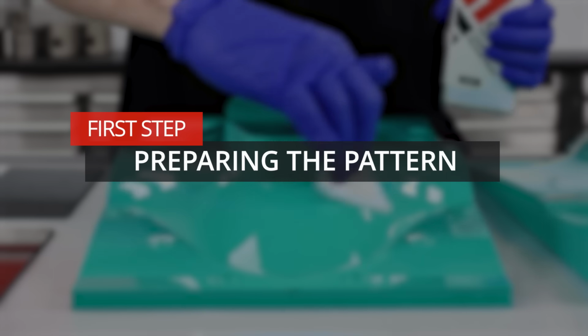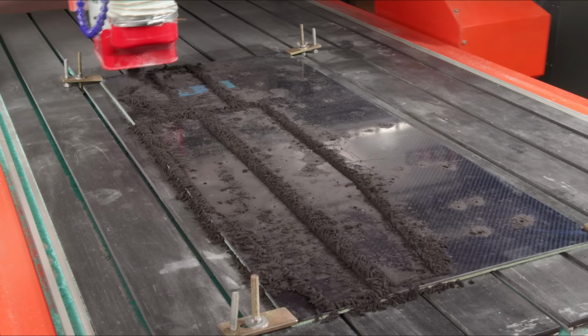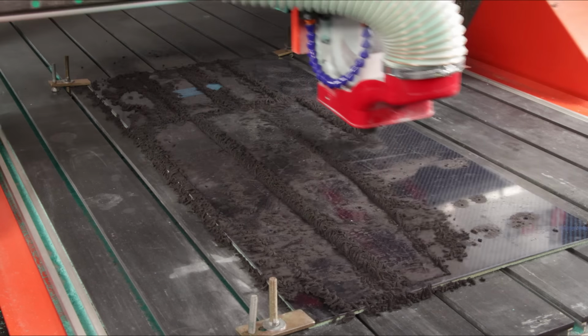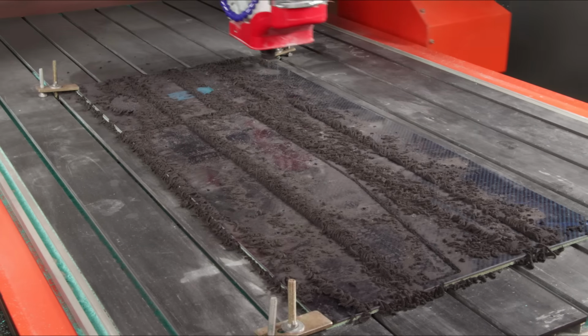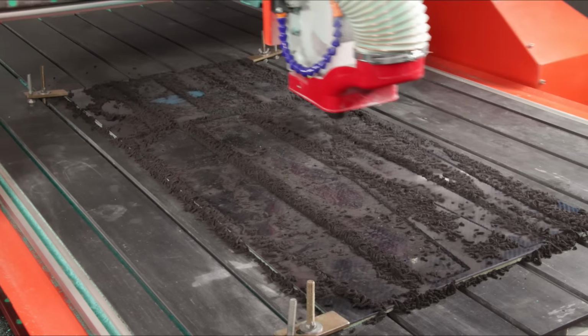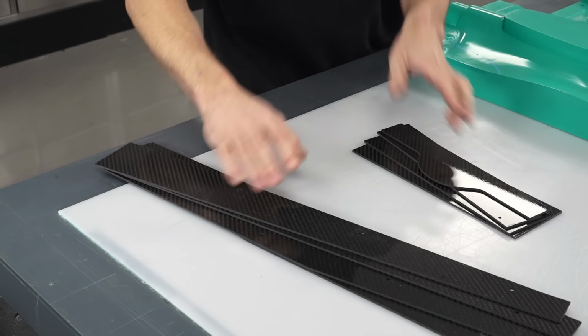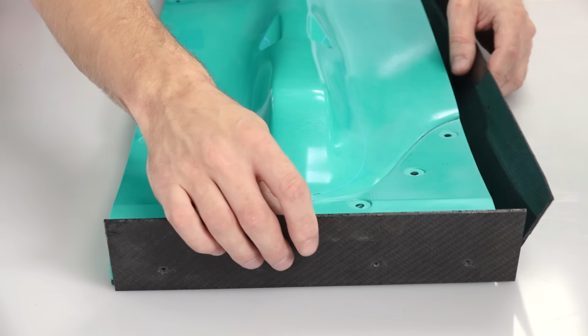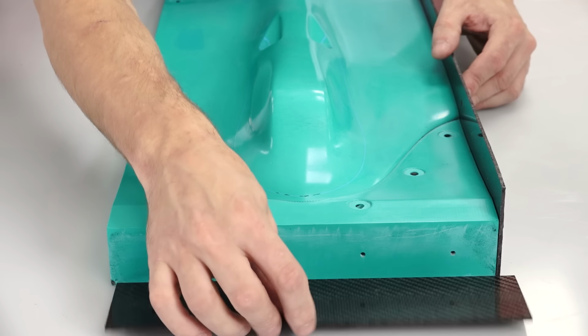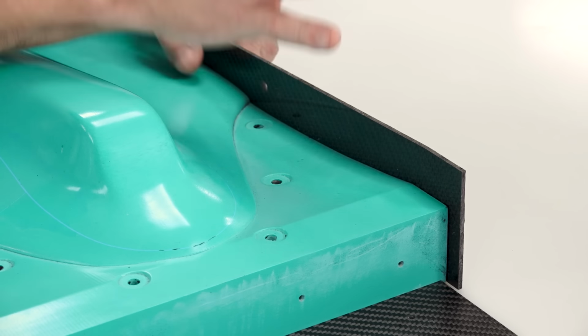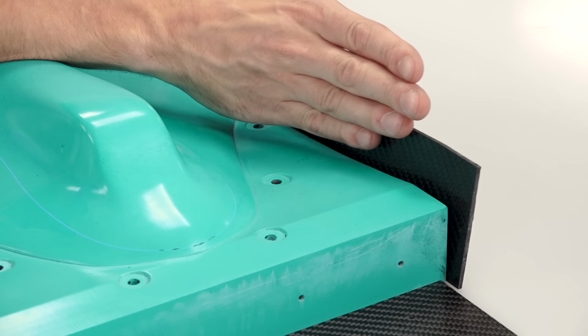I'm going to need some removable shuttering for these patterns. I'm cutting these from carbon fibre sheet on my CNC, but equally they could be profiled in any way from any material that can withstand the cure temperature. The purpose of these shutters is to create a flange at 90 degrees on the mould, and this wouldn't otherwise be possible to form as there's no draft angle on them.